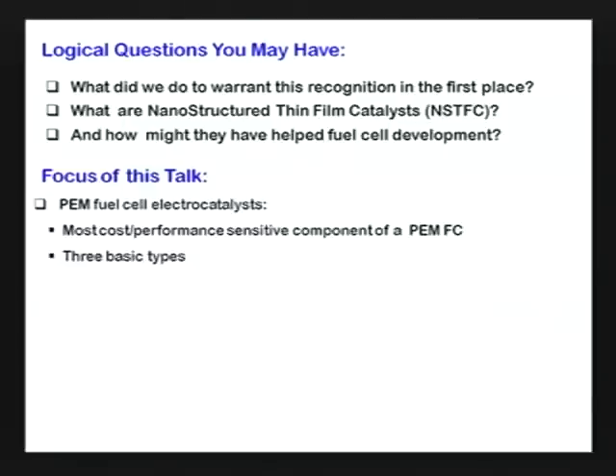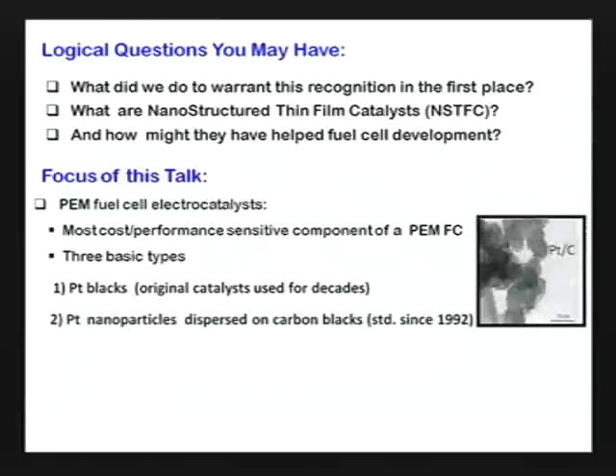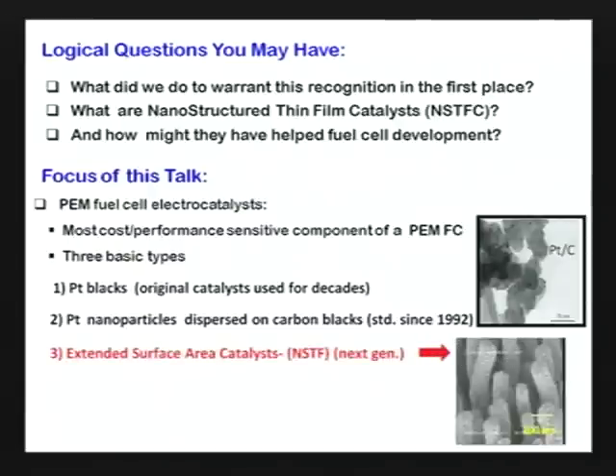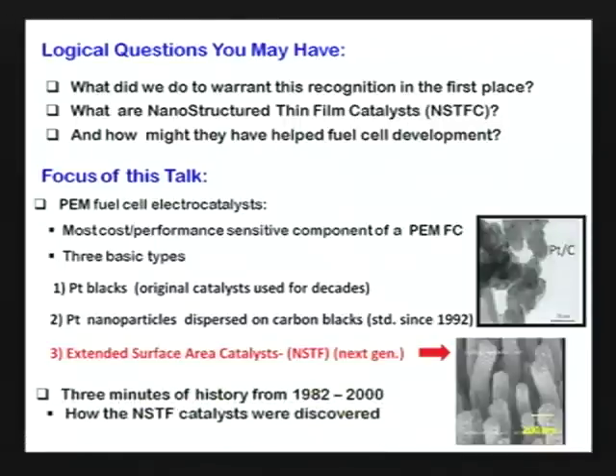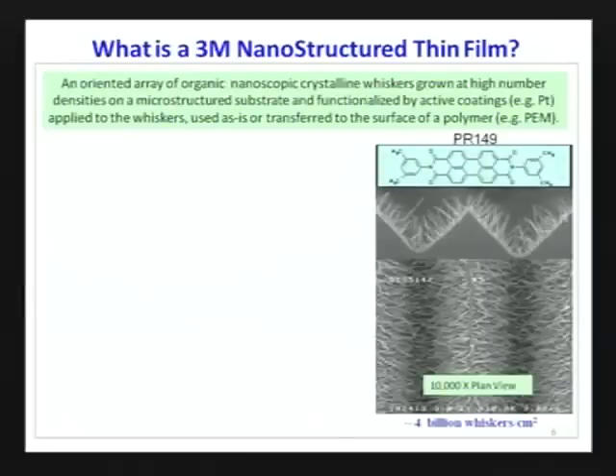There are three basic types of electrocatalysts. First are, of course, platinum blacks, which have been around for decades and were the original things used. Secondly are platinum nanoparticles, or alloy nanoparticles, that are supported on dispersed carbons, which are absolutely the generic standard everywhere in the world right now. But there's a third type, which we call extended surface area catalysts, and for which NSTF catalysts are the first practical example, and we believe this is the next generation. So I'll cover that in the rest of my talk, and then conclude with about 3 minutes of history from '82 to 2000 on how these materials were discovered in the first place.